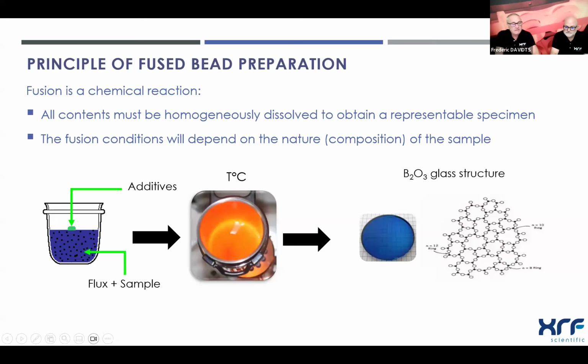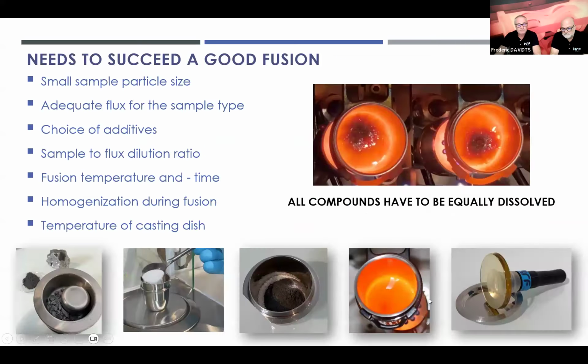So, as mentioned, fusion is a chemical reaction, but it is important that we have a very homogeneous sample. Therefore, we can mix the flux with our sample already. We have special cases where we need some pre-oxidation, so we cannot do this, but in general, we can mix oxidic samples with our flux to make sure that the reaction is way better and faster. And when we see we have a very homogeneous content of our platinum crucible, we will cast it into the glass disc that has this nice boron oxide glass structure.